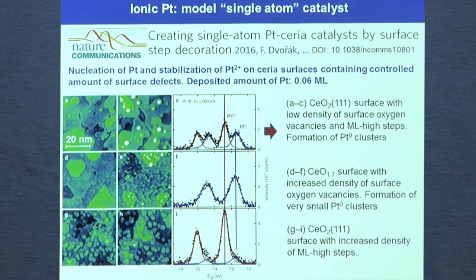And in that case, we have only platinum 0, which means that if the surface is reduced, there is no formation of platinum 2+, which is not very surprising, in fact.